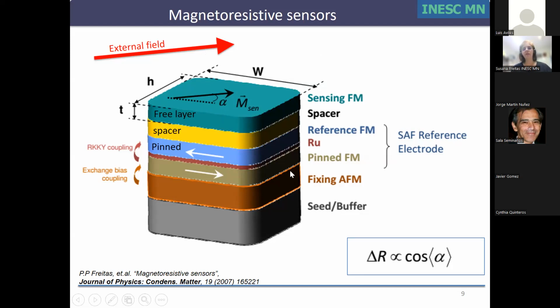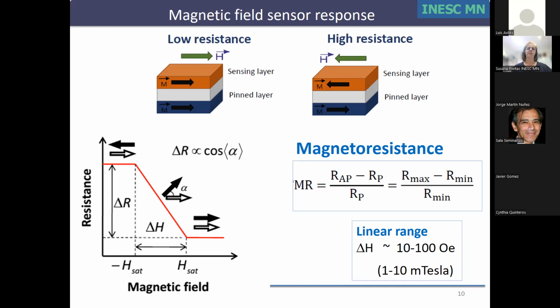So the variation in the resistance of this device, according to an external magnetic field, is monitored as a function of the angle that the magnetization of the free layer makes with the reference layer. So this is a concept from the magnetics perspective, and then we need to use this to create a sensor. And what is a sensor? A sensor relies on a linear transducer between some entity, in this case the external magnetic field H, and then the resistance changes linearly in a certain range with the external field. Of course, if the field is too strong, either positive or negative, we have sensor saturation. So the resistance of the sensor does not change anymore there. But then we have an operation range, which is the linear range for the sensor to be properly working. And this linear range is the area that we can definitely optimize according to the applications.